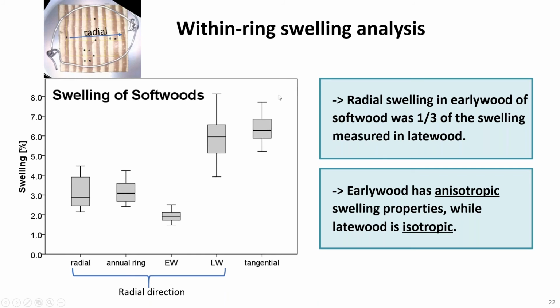So radial swelling in early wood of softwood was 1/3 of the swelling measured in late wood. You see here the early wood and the late wood difference. It's quite a dramatic difference. And the second highlight finding here was early wood has anisotropic swelling properties, while late wood is isotropic. If you compare the late wood, like this is the radial late wood measurement and the tangential late wood measurement, there's no difference, so isotropic.